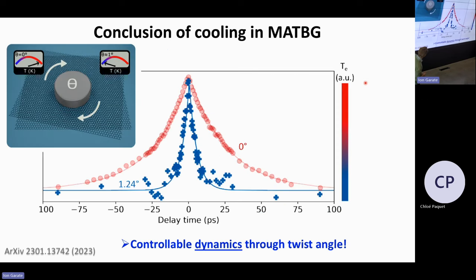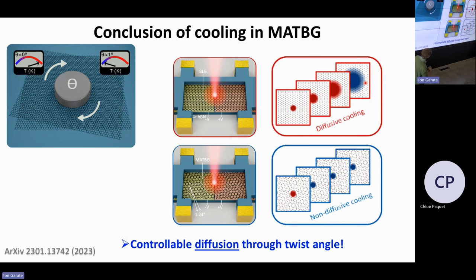So what we believe is that a similar strong electron-phonon interaction through umklapp processes could explain these results that they saw there. So to summarize this part, we see this very strong difference in cooling. So you can actually control the cooling just by changing by 1 degree the top sheet of your bilayer system, and get much faster cooling, which occurs through a novel umklapp-assisted electron-phonon coupling mechanism.